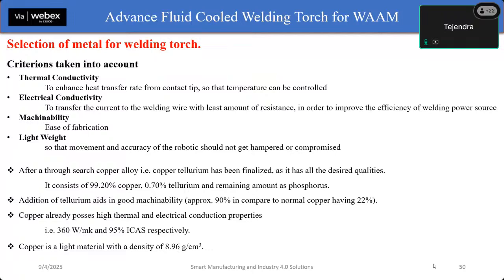So, after thorough research, the material selected was copper tellurium. It consists of 99.2% copper, 0.7% tellurium, and the remaining amount phosphorus. The tellurium also adds the benefit of good machinability. Copper is also a lightweight material with a density of only 8.96 gram per centimeter cube. Hence, the lightweight quality of the component is also there.